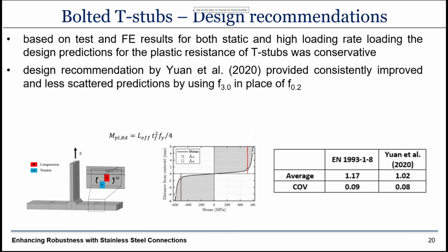Based on the numerical and the experimental results we obtained, we assessed the design provisions of Eurocode 3 Part 1-8 for plastic resistance of T-stubs. They were found to be overly conservative for both static and high strain rates. Similar observations we had made with my good friend and colleague, Dr. Yuan from University of Wuhan in 2020, where we proposed a slight modification that improves the results.